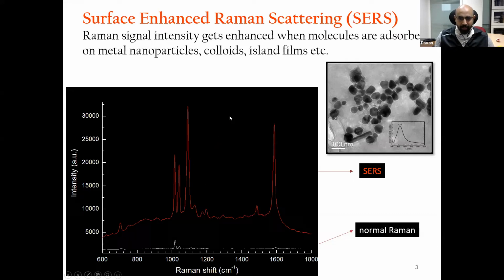There are two important features in this spectral signature. One is, of course, that there is an enhancement in the intensity. The other one is that the modes of vibrations you are observing need not be the same as what you observe for a normal Raman scatter signal. This is one of the very important aspects which may be of very high utility in chemistry, where you would be able to understand the local geometry of the molecule and its adsorption dynamics and characteristics by studying the modes of vibrations on a nanoparticle. This has, of course, turned out to be a very powerful tool in catalysis and other kinds of interaction, where the geometry of the molecule plays a critical role in the conversion efficiency of a catalytic process.